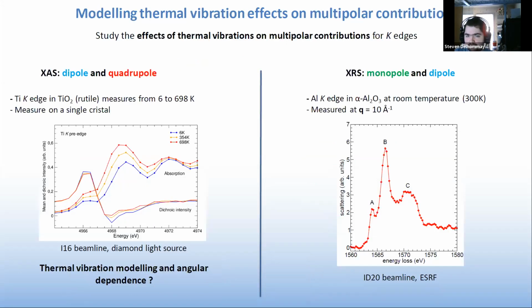The goal of this study more precisely is to study and model the effects of the thermal vibrations of the nuclei on all these different multipolar contributions. And we're going to see that using two cases. So on one hand, we have the measure in XRS of the K edge of aluminum in corundum, so Al2O3, at room temperature, and it was measured using a high value for the Q vector, so that we had access to both monopole and dipole channels. And here we can see the experimental spectra. It was measured at ID20 at ESRF.